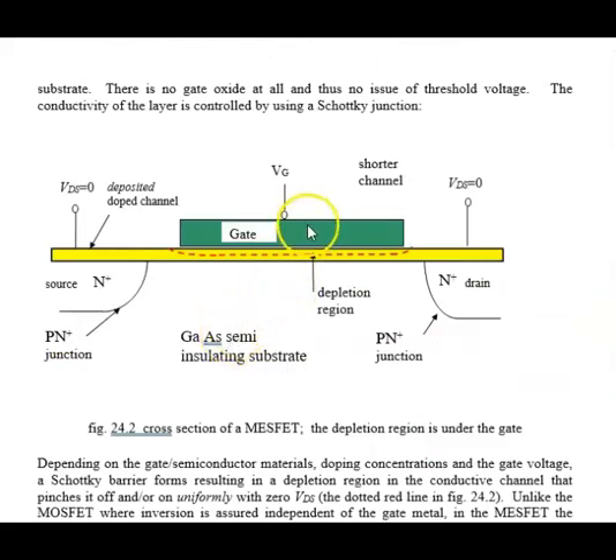Here, however, we have a metal semiconductor. This is a semiconductor, even though it is a deposited channel, it is not really grown, but deposited on top of the gallium arsenide substrate. So generally this will also be gallium arsenide. It's just doped generally about 10 to the 16th. So here we have a metal semiconductor interface or a Schottky interface, and if I don't choose the right material for the gate, I can have an ohmic contact here. So I have to make sure that I choose the right gate metal. Generally for gallium arsenide, gold is a good choice.